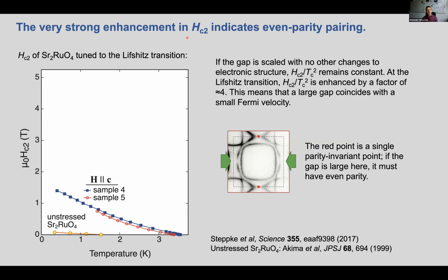So what do the strain data tell us? Data under uniaxial stress show a very strong enhancement in the upper critical field that gives a strong indication that the superconductivity has even parity. So at the left, I showed the data for field applied along the c-axis. In unstressed strontium ruthenate, the upper critical field is below 0.1 Tesla. It's quite small. When we tune it to the Lifshitz transition, the upper critical field is right about 1.5 T as T goes to 0. That is an enhancement of a factor of about 20.